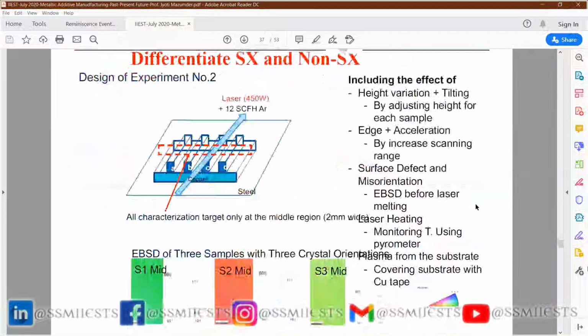And we can also differentiate by looking at the plasma. We can also differentiate the tilting of the plate, what kind of edge acceleration. And by doing the EBSD before and after melting, we can also find out what kind of texture you're growing, what direction the single crystal is growing. So all kinds of information is hidden in the light.